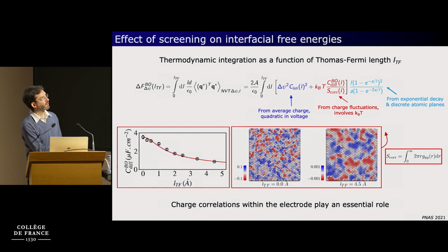It depends on the differential capacitance, which, as I've mentioned already, decreases with the Thomas Fermi length. It also involves a correlation length, which tells you the extent of the charge domains. And as you can see here on this snapshot, it depends on the value of the LTF. And generally, the correlation area increases when you increase the screening length, as you might expect.